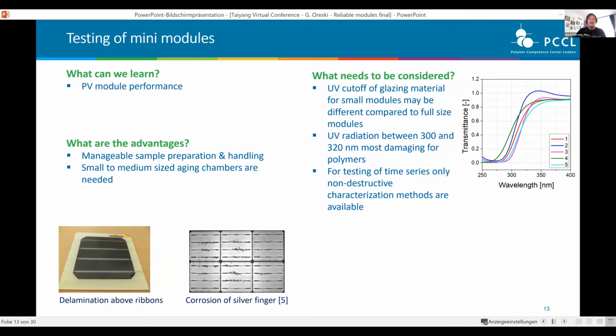That was a mishap that happened to us. We didn't think of, for mini modules, often you don't use hardened glass for handling reasons, for price reasons, you just use standard glass. And then after some time, we found out, oops, we didn't check the UV cutoff. And so we tested like 5 different glasses. And then we saw, okay, the UV cutoff is somewhere between 300 and 320 nanometers of UV wavelength.